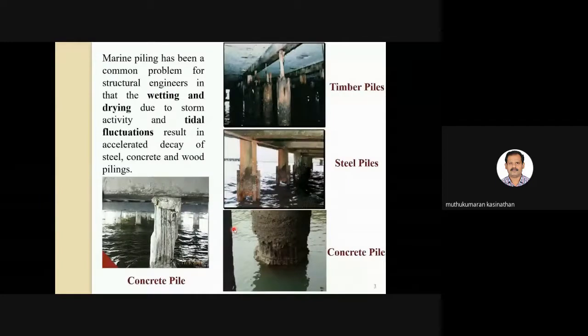And especially when you talk about the marine environment, you are all very well aware that the marine environment is not a steady state water level. It is always subject to fluctuation. During the tidal variation, a particular zone is often subjected to a wetting and drying process. That zone we call the splash zone. The splash zone is very severe against the oxidation process, because often you'll have wetting and drying, and that creates many more issues related to the corrosion of the pile. This is very dangerous for steel piles, but nevertheless, concrete piles are also subjected to danger, especially in tidal variation. So we need to overcome this issue.